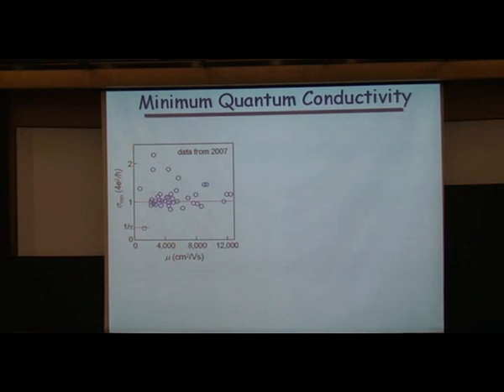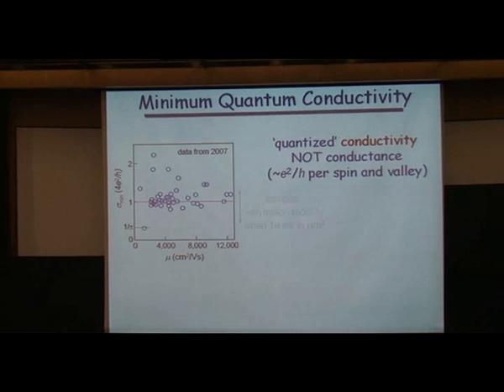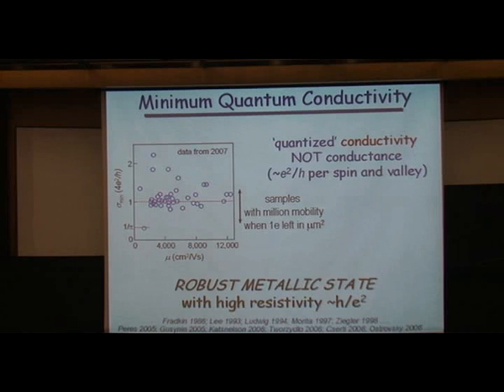carriers. Those are initial data from 3 years ago, different devices, and this is the minimum conductivity we observe in our devices. Now we have these million mobility devices I already mentioned, and still we go to one Dirac electron or Dirac hole, Dirac fermion, and still a single electron within a 1 micron device with plenty of impurities present somehow provides the same conductivity as many of those. Theoretically, 1 electron should provide a conductivity even for a 1 kilometer square piece of material. It's not conductance, it's conductivity, so it scales with parameters. So we called it